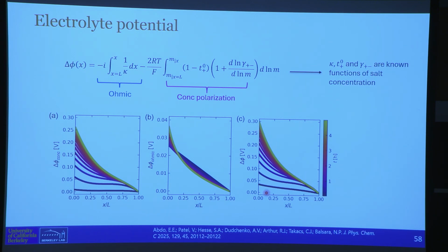So initially, this is at constant current. The potential on the left side is low. That's the gradient of the potential, and then it grows up as a function of time, and that's the steady state potential that Emily gets. Okay. It has two contributions. The ohmic, given by the conductivity, plotted here, and the concentration overpotential plotted here.